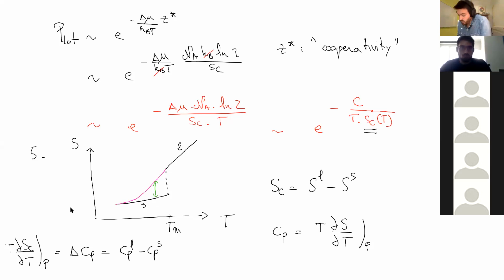But based on what I said previously, if you prolong this line of the supercooled liquid state, it seems that there is a crossing point at a certain temperature that we call the Kauzmann temperature, at which and below which the configurational entropy will become smaller than 0. So it would mean that the entropy of the liquid will become smaller than the entropy of the solid. This is not possible. The solid is the most ordered state in condensed matter, right? It's an open problem, so I might be wrong in what I just said, so be careful. But according to our intuition, this is not possible. The entropy of a liquid should always be larger than the entropy of the solid.